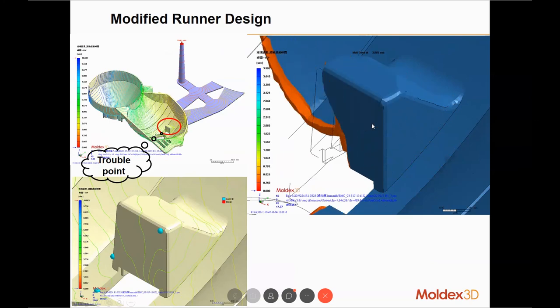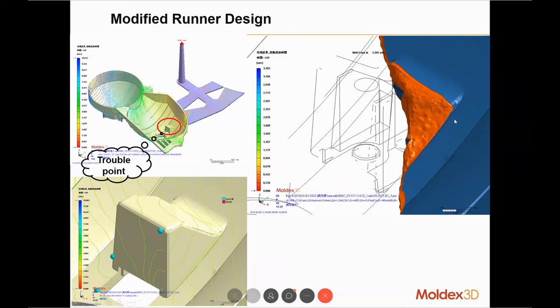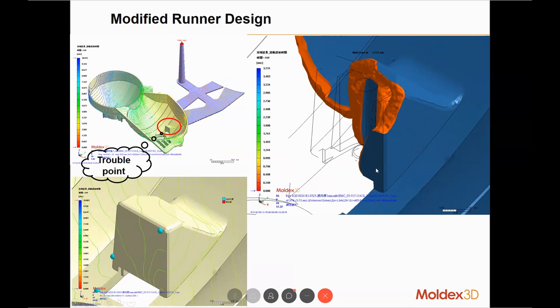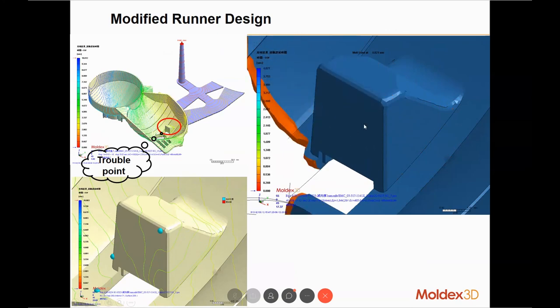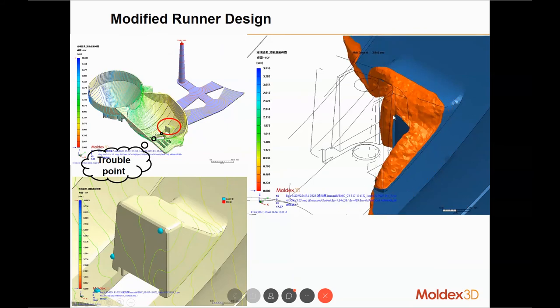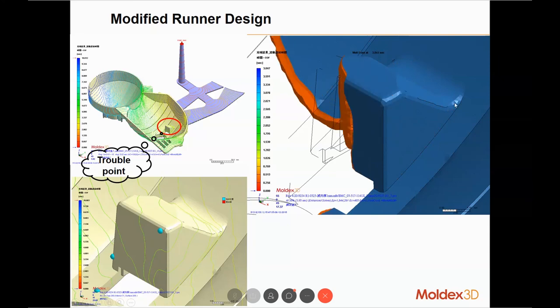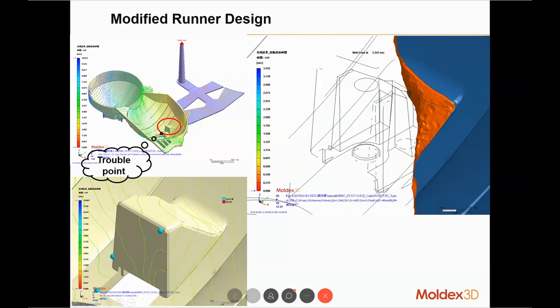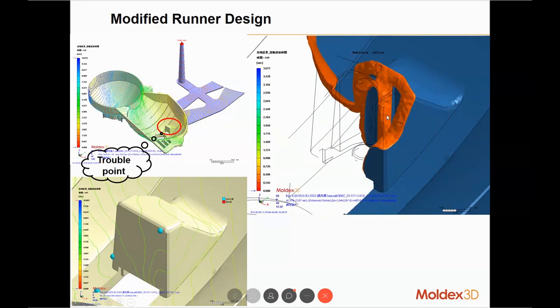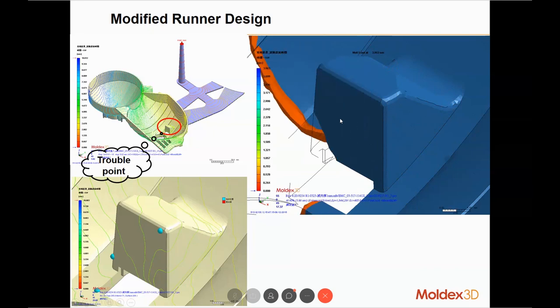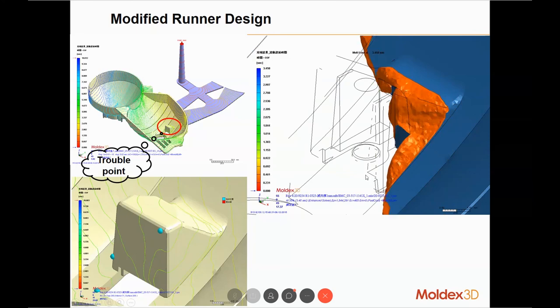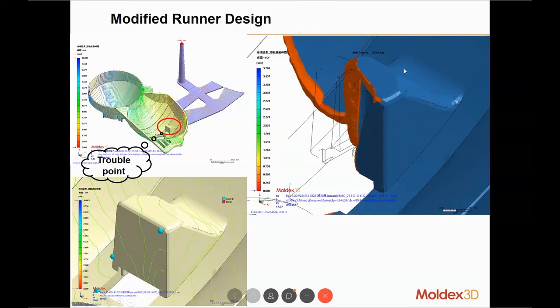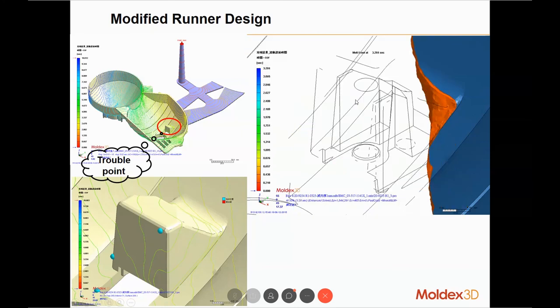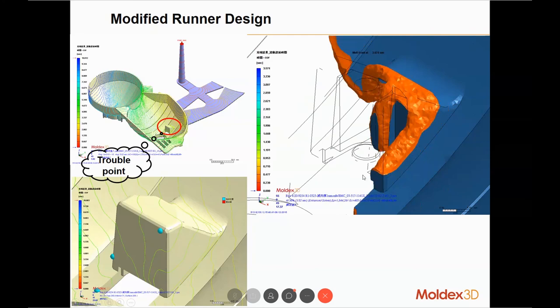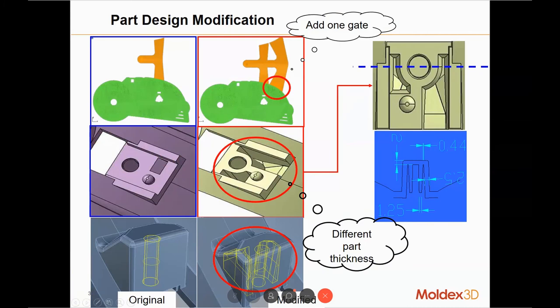After modification, they were able to change the melt front, the hole filling pattern, so that in this region, the melt doesn't cover the bottom part first and create any closed air trap on the top, but actually it flows from the right side to the left side. So as you can see from the animation, there's absolutely no closed air trap, no closed region that is created during this filling stage in this geometry, which allows all the air to escape from this region. So here are the modifications that TYC has done.